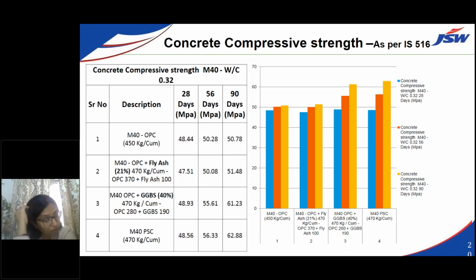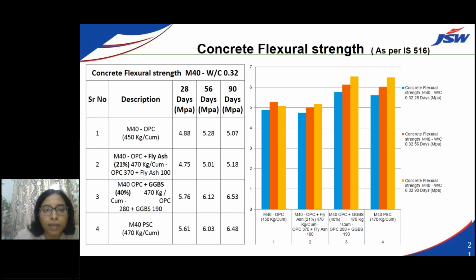But the best part about slag, the long-term strength of the products of slag will give you a higher compressive strength as compared to fly ash based or OPC based concrete. This is the compressive strength. Then we are going into flexural strength. Here also you can see the flexural strength of M40 OPC and M40 PSC. You can see the flexural strength are also improved here, and it is in line with OPC, if not better.